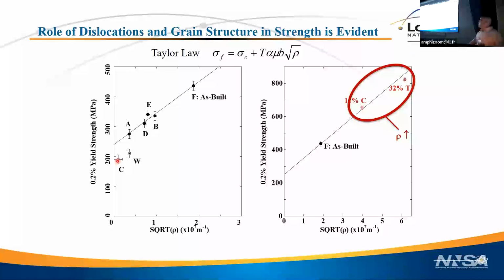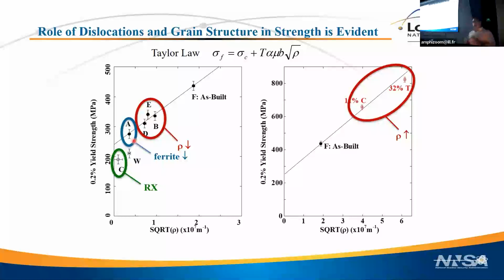So the conclusion that you would draw from this is that most of the strength of the material, which is what you're plotting on the y-axis, is due to the elevated dislocation density. If I take those dislocations away, the material loses strength. When I take the ferrite away, which is sample A, that doesn't change the strength at all. So that tells me the ferrite wasn't playing any role in the strengthening of the AM material. Finally, if I recrystallize it, if I change the shape, the morphology of the grains, that does take away a significant portion of the strength.